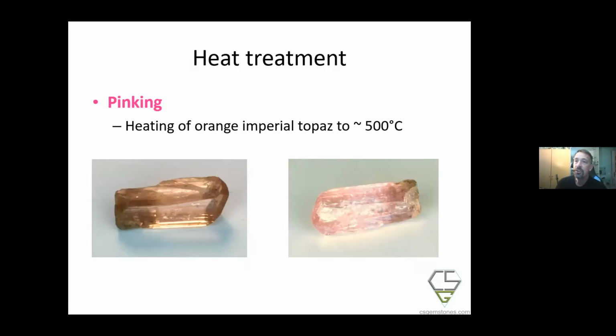But there is not only radiation treatment, there's also a second treatment, which is very often done in Brazil. Why in Brazil? Because it is specific to these Ouro Preto topazes. Ouro Preto topazes do not only come in this wonderful orange or pink hues, many of them have this brownish coloration. And this brownish coloration is due to the fact that we have some pink due to the chromium, and we have some color centers, which cause the yellow color. And if you mix the yellow and the pinkish, then you get this orange in the best case, or some brownish like this.